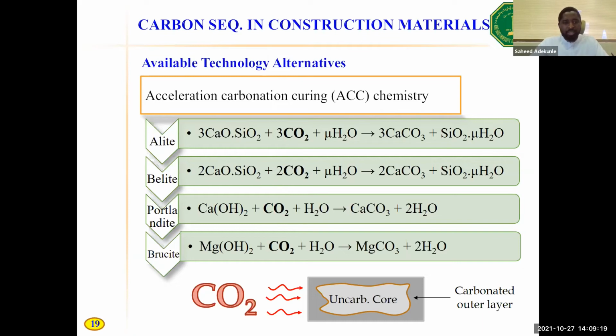In addition to that, the chemical reaction of ACC is exothermic. And the heat released from the reaction going on in the outer shell also radiates towards the core. The release of heat to the core actually enhances the hydration process to make sure that the hydration process can proceed faster. And this is a double benefit: utilization of carbon and enhancement of technical performance of CO2 cured concrete. So this is the workings of accelerated carbonation curing technology.